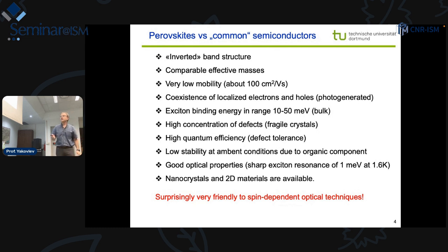Magnetic fields help with that. I will show that. Exciton binding energies are in a reasonable range, 10 to 50 millielectron volts in bulk, and can be hugely enhanced in nanocrystals or in two-dimensional materials. There are high concentrations of defects. The material is fragile, it's sometimes not easy to handle or even to polish. And surprisingly, despite the high presence of defects, the material has a very high quantum efficiency. Emission is incredibly strong. This is explained by defect tolerance: the defects do not like to be within the band gap, they are outside the band gap. And that's why, if a carrier is relaxing energy to the band gap edge, the only way for this carrier to go out is radiative recombination.